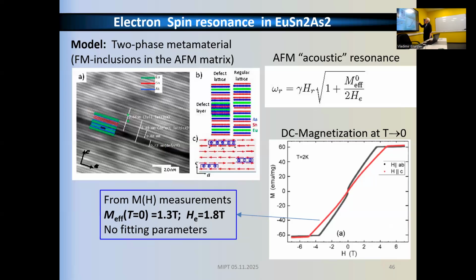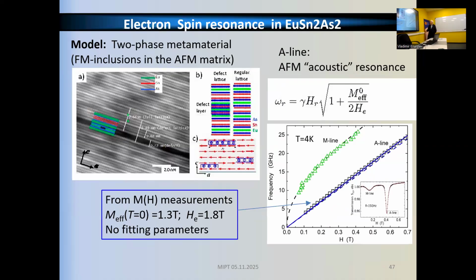Nevertheless, for the regular AFM acoustic resonance, we have a known dependence. It was used already before, and there are no fitting parameters because everything that comes in here, the effective magnetization of the antiferromagnet and the exchange field, can be immediately found from the DC magnetization curve and determined in an experiment like this. Having no fitting parameter, we immediately fit the frequency versus magnetic field dependence that was measured by Igor Golovchansky, but this has actually already been done by him. So far, there is nothing new, and we move further.